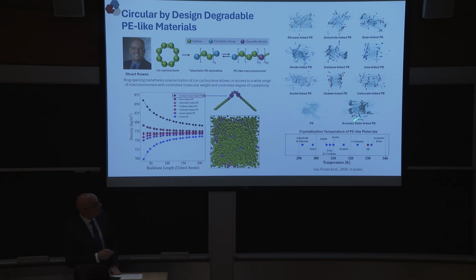So you really want to engineer switches that have the right mechanical strength, the right torsional barriers, and that are susceptible to very specific temperature ranges or pH ranges, because otherwise they just degrade very, very easily. So the moment that I say degrade, I have a problem, because all of the models that I'm using are classical. They cannot capture chemistry, chemical reactions, bond breaking, or bond formation. So we need to use something better than that.